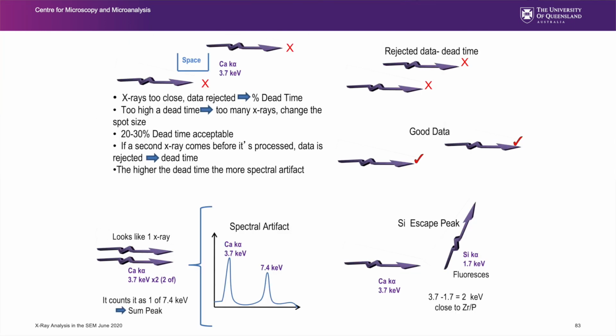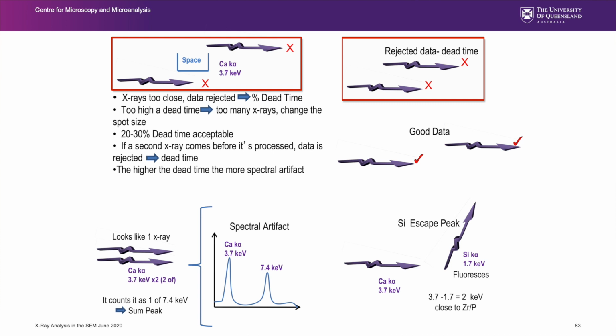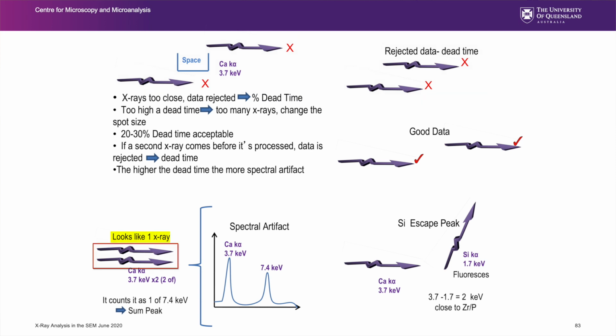There are 2 other things that can happen, and they're shown down the bottom of that slide. First of all, if I get 2 X-rays that land too close together, I've got 2 pulses too close together, and I reject both pulses. That's dead time. What can sometimes happen is 2 X-rays can land at exactly the same time. And my detector doesn't realise it's 2 X-rays because it doesn't see 2 pulses, because they land simultaneously. For example, I get 2 calcium K alphas landing at 3.7. So rather than count them, which I should, as 2 3.7 keV X-rays, my detector counts them as 1 of 7.4 keV X-ray. It adds the energy together, and that's called a sum peak, a summation peak, an addition peak.